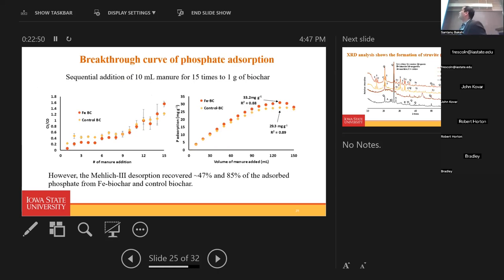We did a sequential addition of manure onto the biochar, and then we did the breakthrough curve, where Ct by C naught becomes one, in the iron biochar and the control biochar. We found that around 29.3 milligram per gram with the control biochar and 33.2 milligram per gram with the iron biochar of phosphate can adsorb onto the biochar. However, the Mehlich-III desorption recovered around 47% and 85% of the absorbed phosphate from iron biochar and control biochar. So the iron biochar retains more than 50% of the absorbed phosphate in the system, whereas the control biochar is releasing most of the absorbed phosphate from the system.